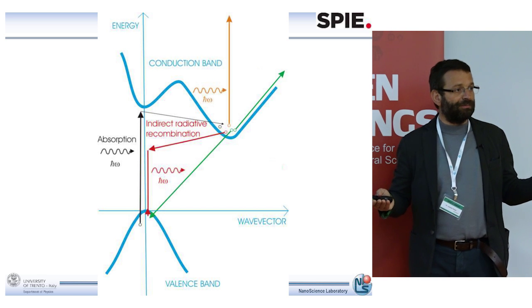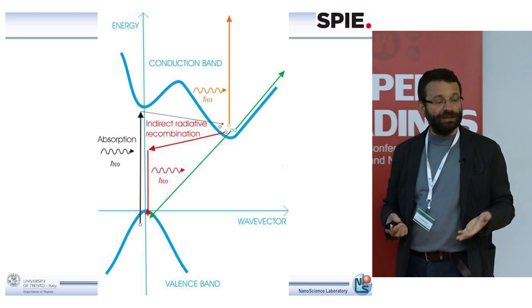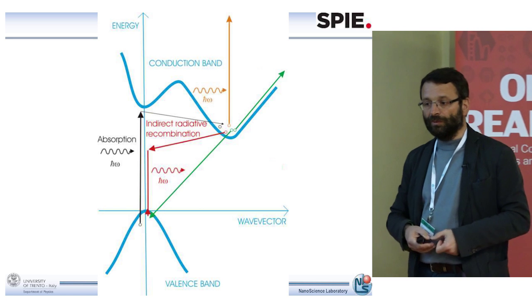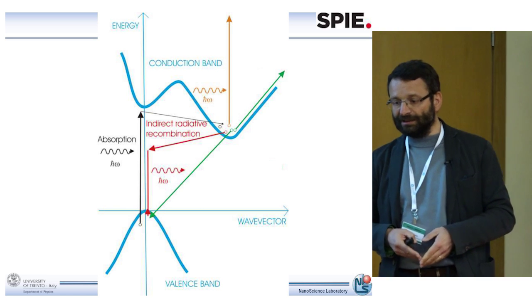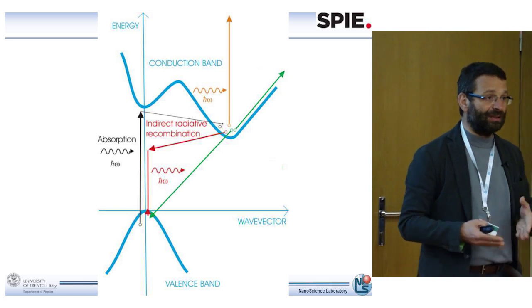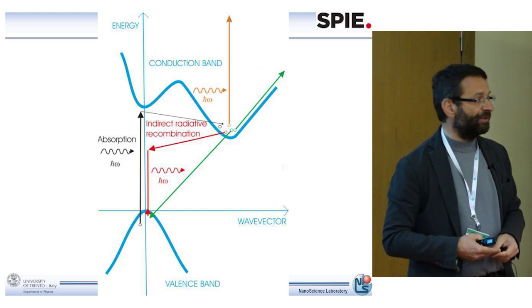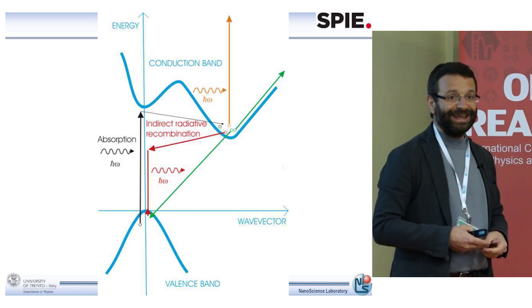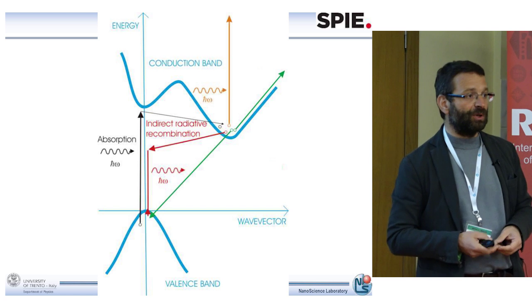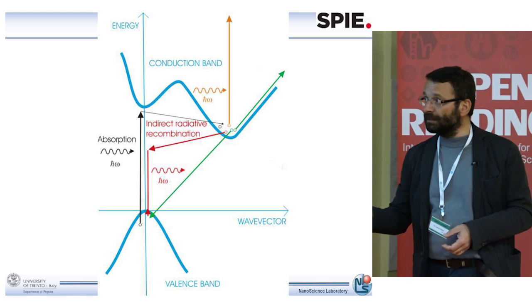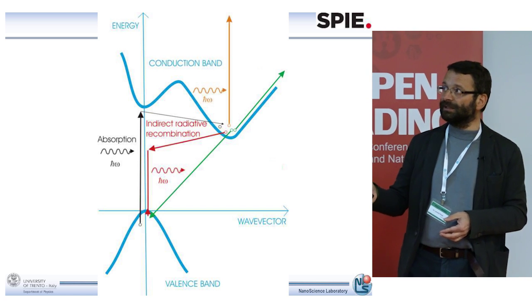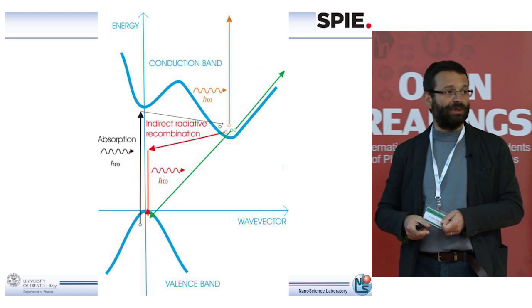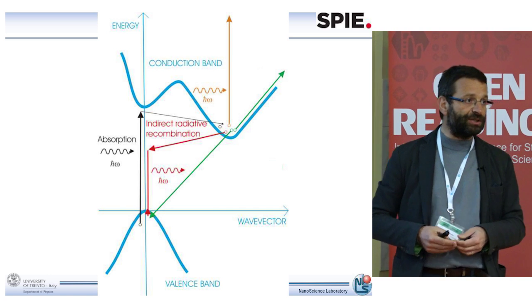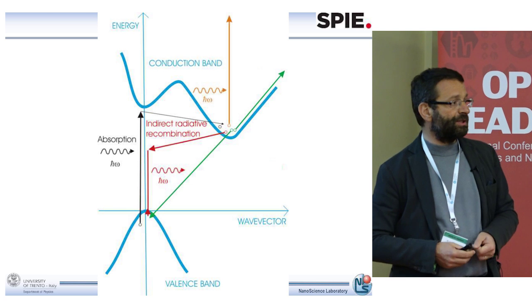Otherwise, you cannot recombine. This is the big difference between silicon, which is an indirect band gap semiconductor, and III-V semiconductors that are direct band gap semiconductors. If you want to make a laser, you use a direct band gap semiconductor because in the direct band gap semiconductor, the direct transition, the recombination between electrons and holes, is very easy. In silicon, it's not.